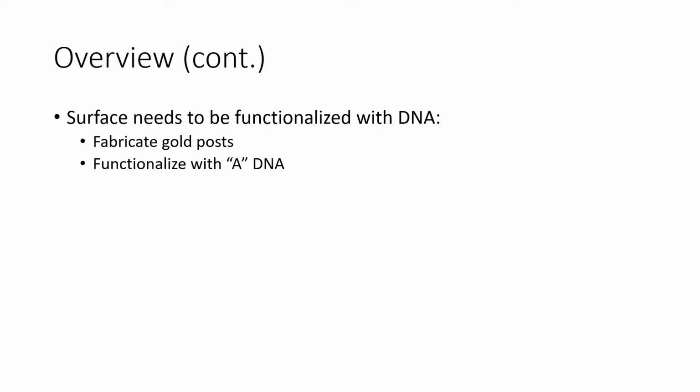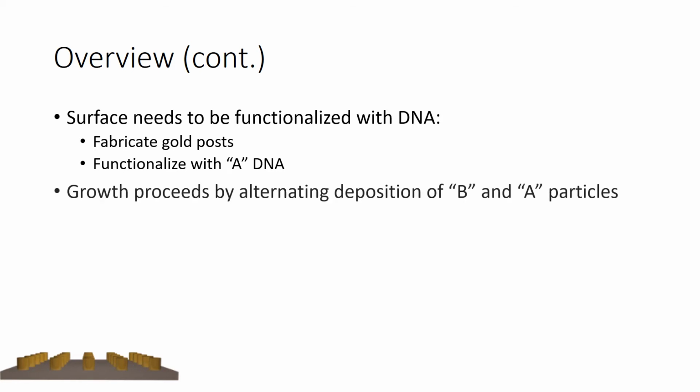In order to form a monolayer of nanoparticles, the surface needs to be functionalized with DNA. To accomplish this, gold posts are fabricated on a substrate, and these gold posts are then functionalized with A-type DNA. These gold posts then behave like a perfect monolayer of A-type nanoparticles.